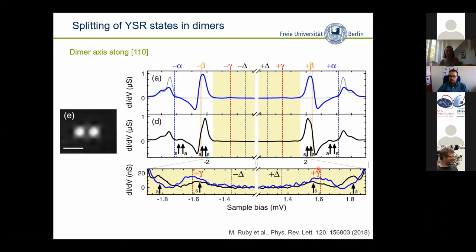After having seen this is possible theoretically, we want to ask whether this happens in experiments. We put two manganese atoms roughly one nanometer apart. The upper panel shows the spectrum for an individual isolated manganese atom — the very pronounced Shiba states labeled alpha, shoulders close to the superconducting gap edge, and very faint resonances. When you measure on one of these atoms that has a neighbor, the overall appearance is very similar, but looking into details you start to see small splittings — two peaks instead of one peak — with pronounced shoulders on the beta state.